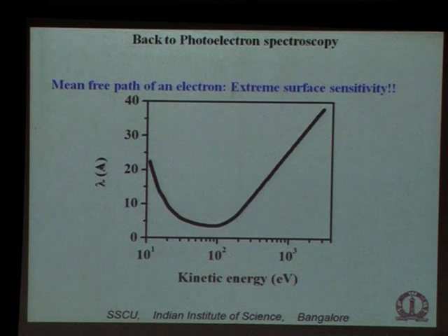But in the high energy, and since you're most of the time in the high energy, even this 100 electron volt is a huge energy for doing internal electronic excitations. And that's where electron-electron Coulombic interaction causes a lot of inelastic processes. In fact, the technique that I did not cover, electron energy loss, is exactly that. You bring in a high energy electron and excite all these internal ones and see the structure.